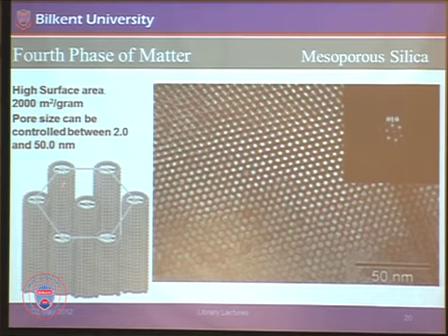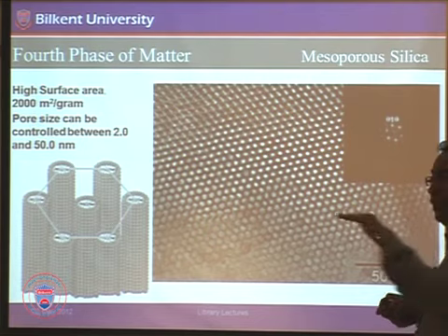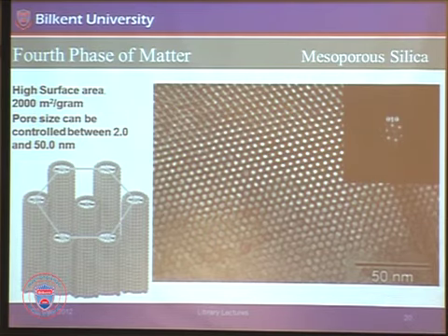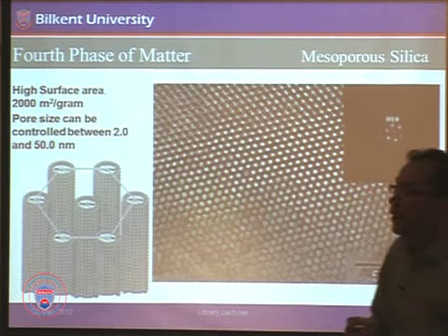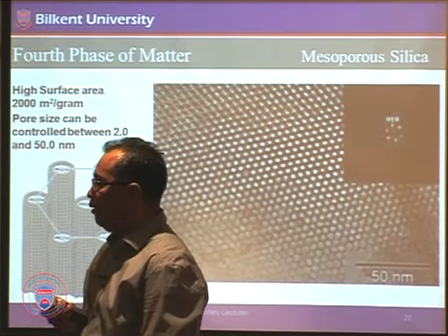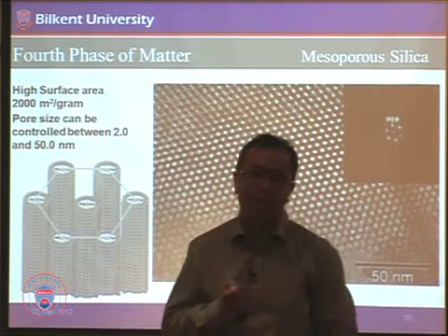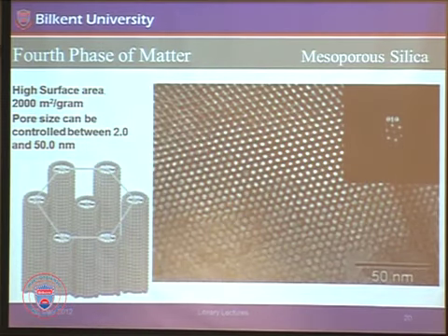And you can basically burn these surfactants out, get a template of that. This is a TEM image of a silica. These white spots are those domains which are burned out, and the darker domains are silica, glass, what we know. But you have holes in these glasses, regular holes going through the glass. And these holes are in the range of the size of these, you can tune between 2 nanometer to 50 nanometer. There is no technology that can create this small. Current technology, those expensive electronic technologies, are in the range of tens of nanometer. The smallest are typically in tens of nanometer.